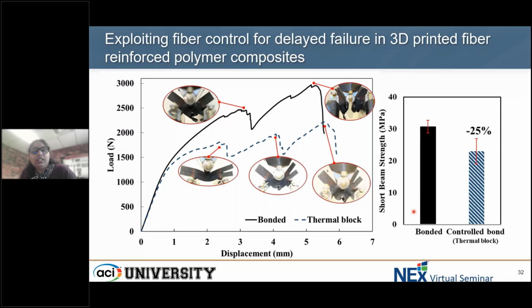So if you see this particular test here, this is an interlaminar shear strength test for the different kinds of bonds. In a completely debonded, we are not able to perform this test because the failure mode is slip. So in the bonded configuration for this interlaminar shear strength, a controlled bond is a 25% reduction in the bond strength itself. So of course the bonded and the control bond differ in terms of bond strength, and this is a way to quantify it. These are ASTM standard tests.